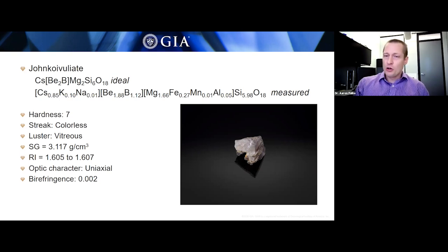In terms of the gemology and mineralogical properties, the new mineral has a hardness of about 7. It has a colorless streak, vitreous luster, a specific gravity of 3.117, refractive index of 1.605 to 1.607. It's uniaxial, with a birefringence of 0.002.